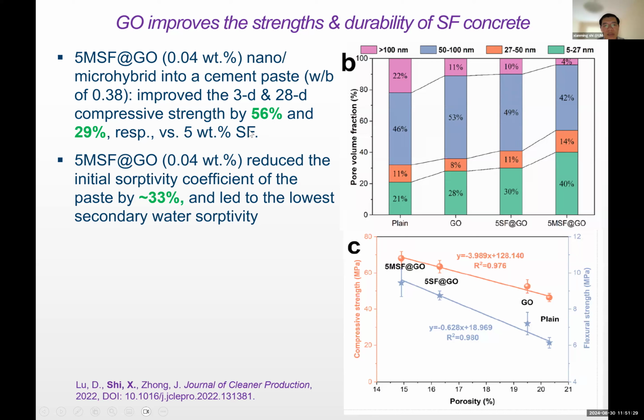So again, it's a significant improvement, but what's even more interesting is that this kind of approach reduced the water absorption by about 33%. The water absorption basically is an indicator of how fast water gets into the concrete. Again, we're talking about a solid sponge here. And one thing we also did is characterize the microstructure of this solid sponge, so to speak.